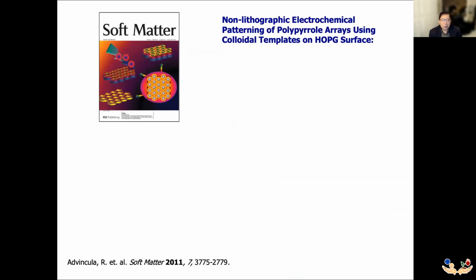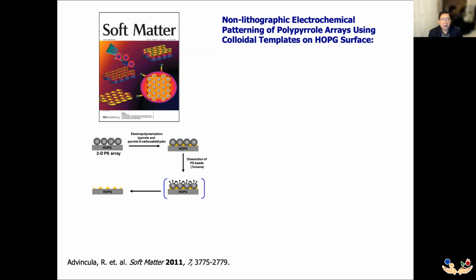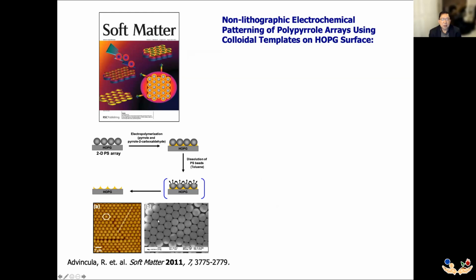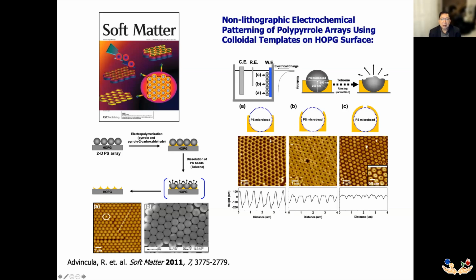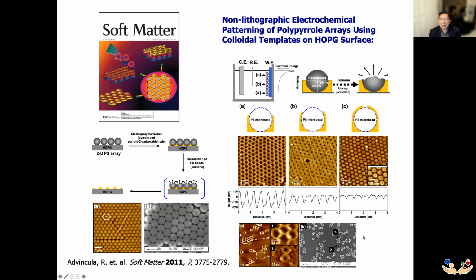Another templating method we used was colloidal nanosphere lithography, where we would prepare colloidal spheres of latex particles using a Langmuir-Blodgett type of deposition and then growing conducting polymer on the shadows or the fringes of this array. So what you see here, for example, is a hexagonally packed structure of perfect spheres, and we happen to grow the polymer around it in a beehive pattern, half dome or full dome, or we can even harvest these capsules, as you can see here, after we prepare them by potentiostatic deposition.